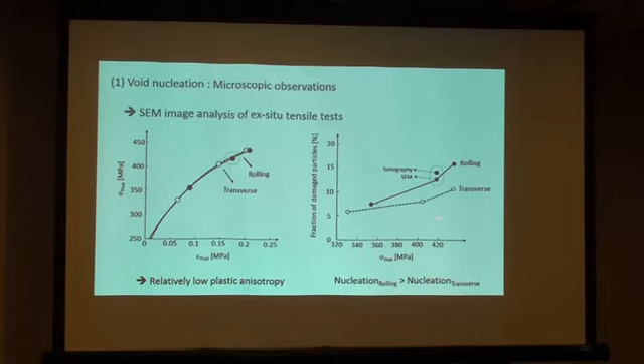If you look at the fraction of damaged particles, you see that in the rolling direction, for the same stress within the matrix, the fraction of broken particles is higher, because those particles tend to get aligned with the rolling direction, and this increases the stress mismatch between the particle and the matrix.